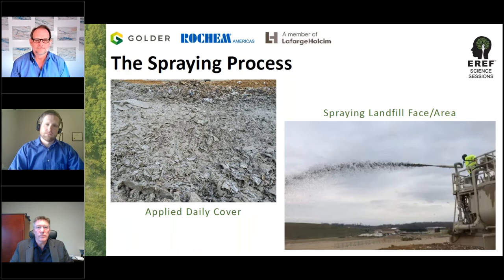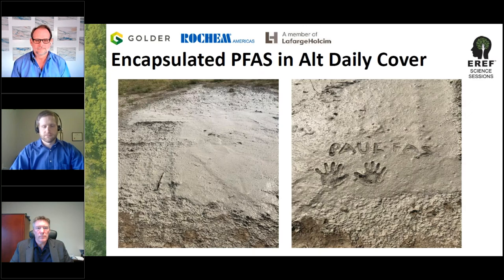What I really like about this final mix that we came up with is that it's a slurry, as you can see, but once it's on the ground, within about 30 minutes it starts to firm up. By the next day, when they're ready to put waste back on the face of the landfill, I call it peanut brittle.